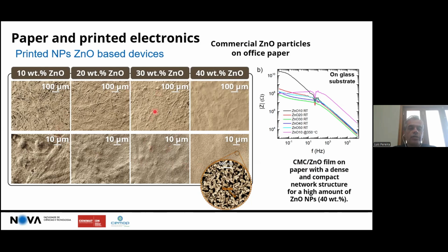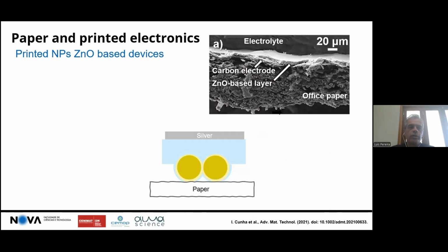In this case, you see the nanospheres, but you see also the concentration of zinc oxide nanoparticles that you need to add to the ink in order to get the proper surface coverage. And so the best results, and the results that I presented so far, are with 40% weight percentage in the CMC ink. And you see that with that, we can even get low impedance at room temperature without requiring further annealing after printing and ensuring proper percolation. So it's a very important point because, as I mentioned, you don't need to heat, you just need to dry the water that is the solvent of the CMC. That can be done in a convection oven or roll to roll on the web.